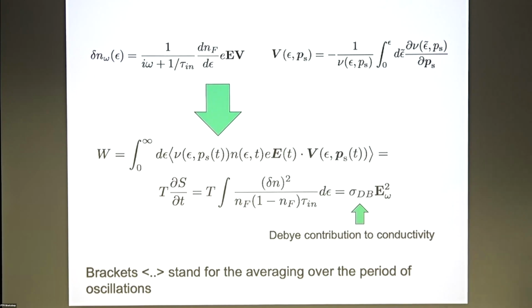Okay. But this is the kinetic equation for quasi-particles. Look, I'm giving you an answer. If you want me to explain how it works, I can give you a hint. The relaxation mechanism is proportional to the longest of the relaxation times. If you go to small temperatures, the recombination time exponentially increases and the concentration exponentially decreases. As a result, this exponent will cancel. But the frequency interval where it happens will be exponentially small. That's my answer. Probably we should think about finite temperature for now, right? Right. The effect doesn't exist at 0. Forget about 0. Think about finite. Okay, thank you.